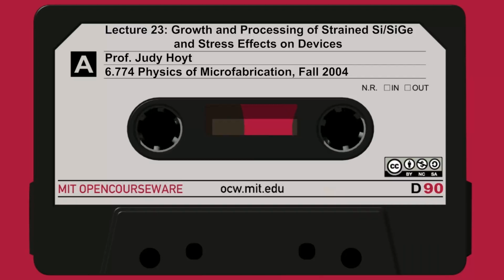Then we need to know, once you know the sheet resistance, the nice thing is that it tells you the resistance going through a square. You just use geometry considerations. How many squares does the current go through in flowing from this point here to the contact? Well, it's a 1/2 micron long, and it's a micron into the page. So that's a 1/2 a square,